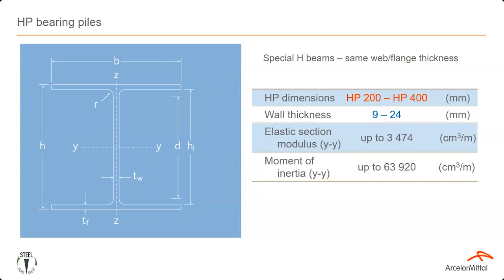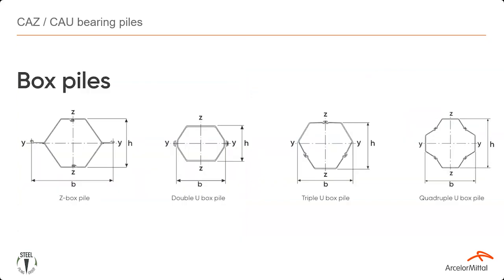And then we've got HP bearing piles as well. So we've made those as well. And you can get dimensions from 200 mil to 400 mil. And you can often find those with wall thicknesses of between 9 and 24. And they're quite useful if you have got a key wall system and things like that.